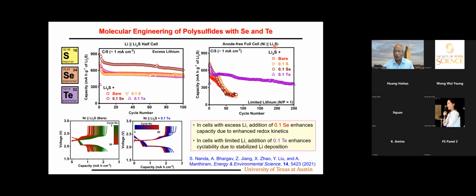Only the lithium is coming only from Li2S. So this is the best way of understanding what is doing what, because we do not have a lot of lithium floating around. Here it is not limited by lithium because we have too much lithium. So selenium is trying to show up its advantage. Here, lithium is the limiting factor, so selenium advantage is not seen. So tellurium is doing something that makes the lithium cycle better than selenium or without having any tellurium.